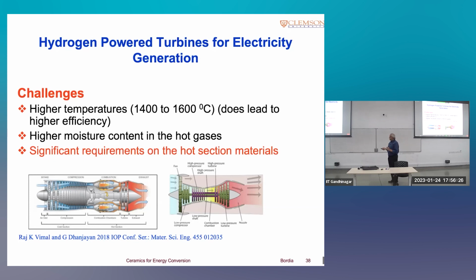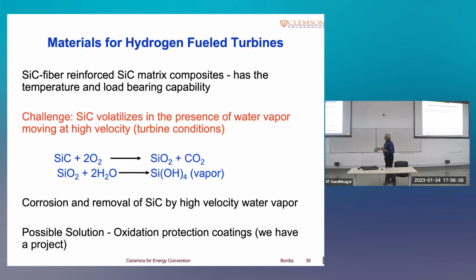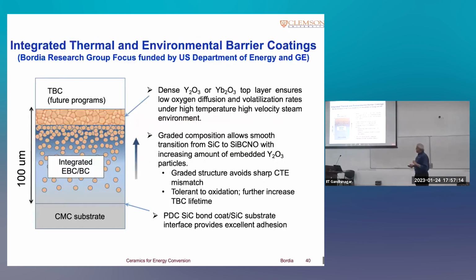So what the industry is looking at are ceramic materials. There's a lot of interest in silicon carbide composites, making turbine components out of this composite. It has the capability to go to the temperatures and handle the loads that are needed. The problem is that silicon carbide itself oxidizes in the presence of steam. It becomes silicon dioxide, and then silicon dioxide in the presence of water vapor converts to silicon hydroxide, which is a vapor, so it just gets swept away because of the very high velocities in a steam turbine. So in my group, we are working on oxidation resistant coatings for silicon carbide.